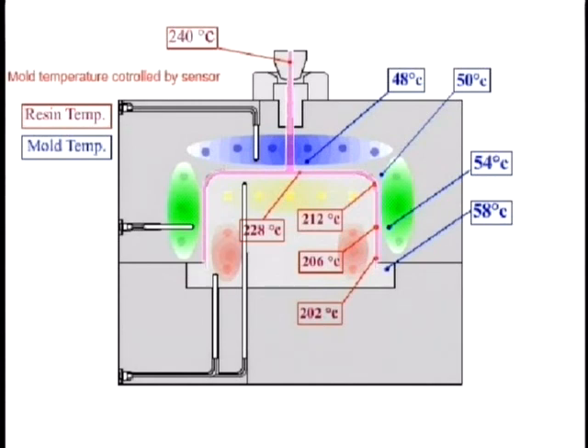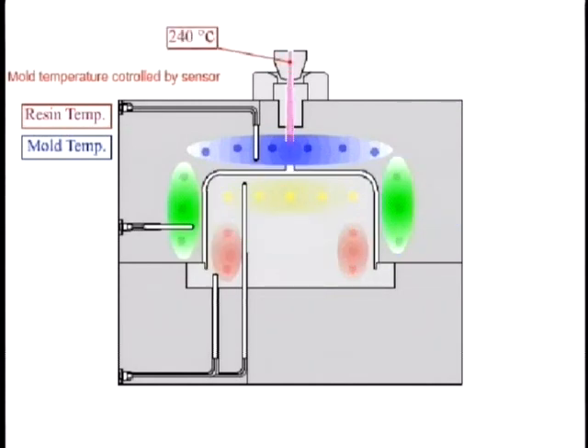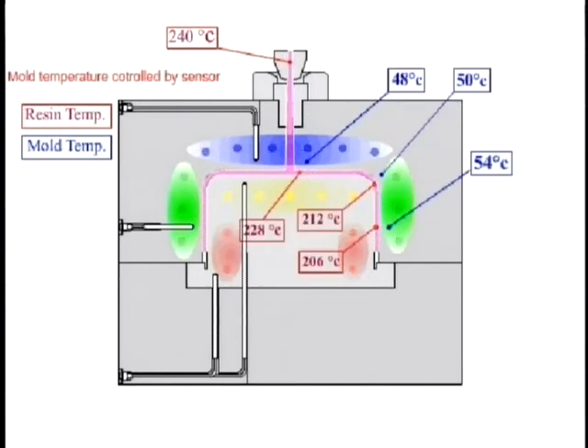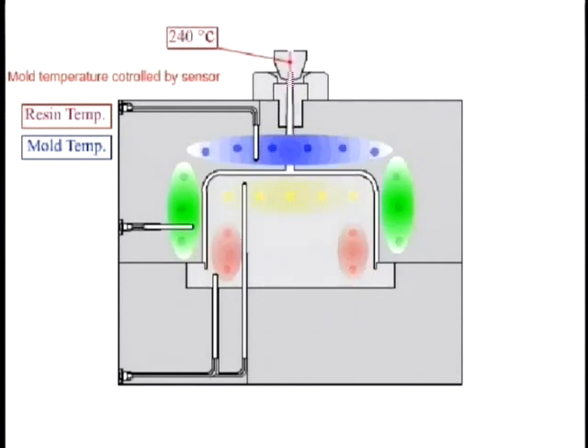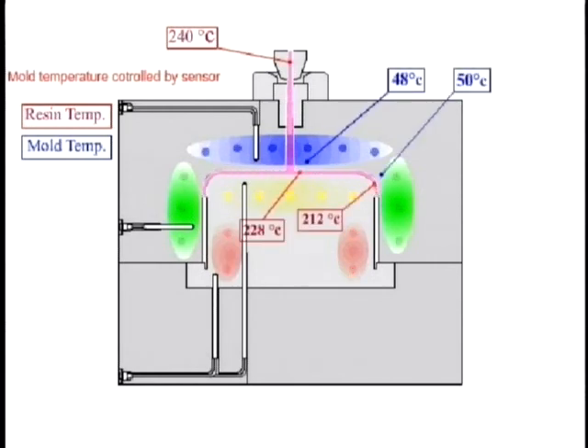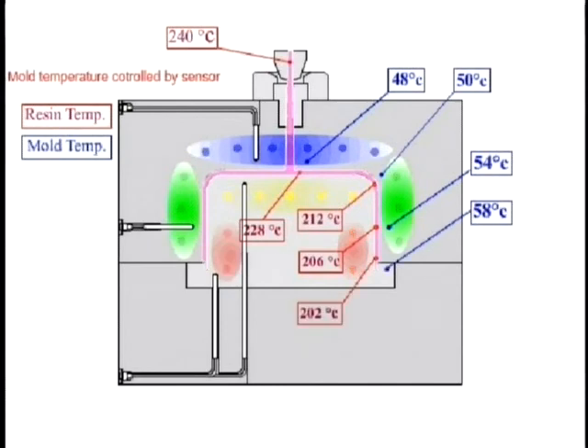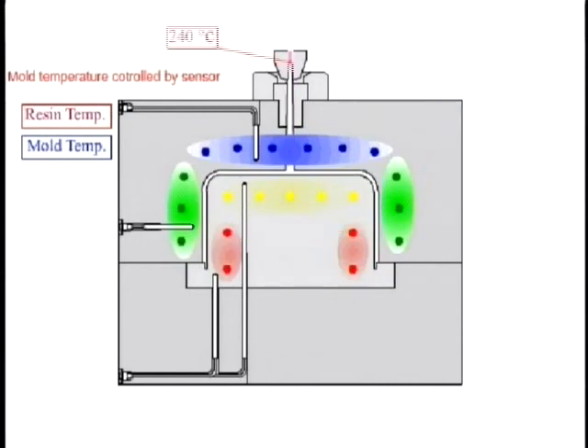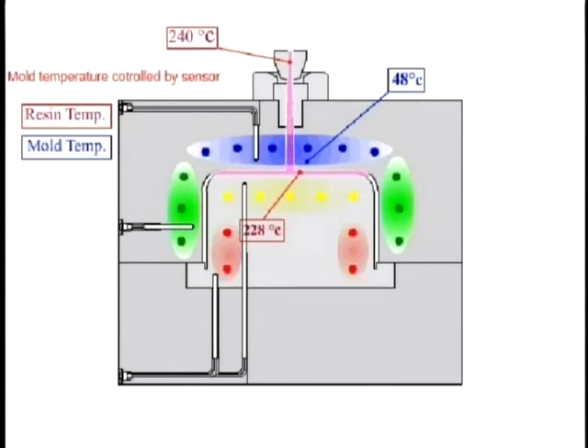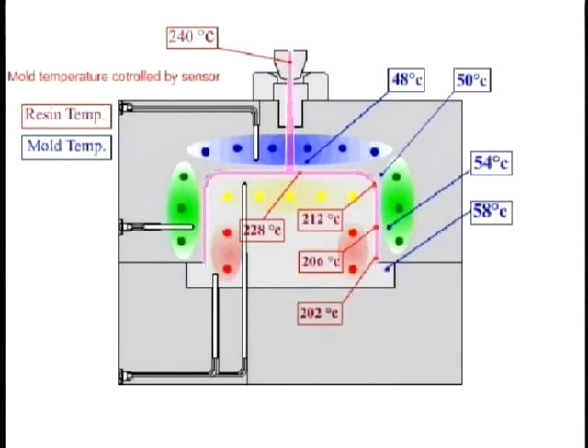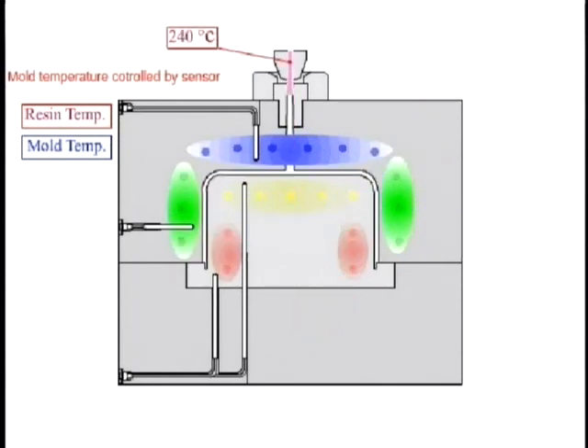For controlling the temperature by zone, 2 temperature sensors each are installed on the fixed side, cavity, and the moving side, core, respectively, of the molding unit in the mold, the high temperature zone of the mouth of the gate, and the edge of molding products. The cooling circuits are classified, and the mold temperature by zone is managed individually. By controlling the mold temperature so that the zone of the gate is 48 degrees and the zone of the edge is 58 degrees for preventing the solidification of resin, it is possible to produce a finished product from the first injection product, since resin with a temperature of 202 degrees is filled in.